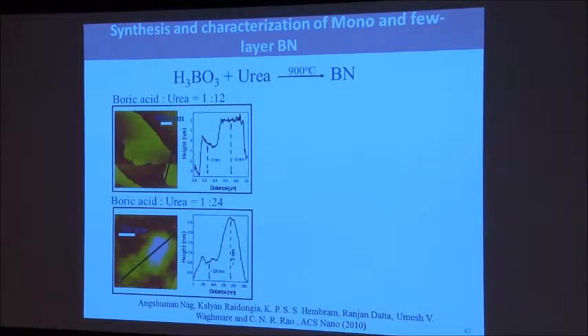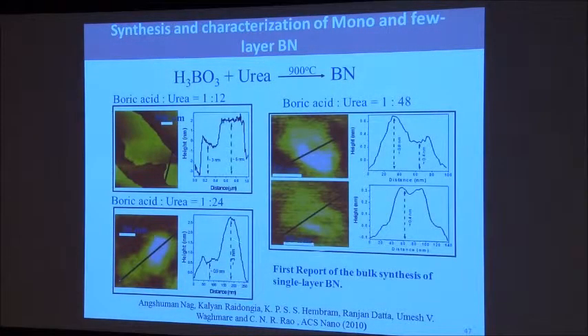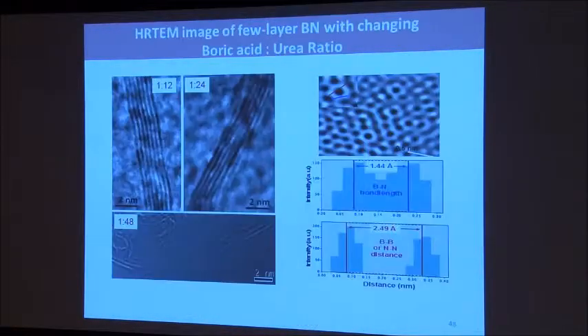Some years ago, 2-3 years ago, we made a very nice boron nitride by a simple high temperature reaction. A lot of people use this method. A single layer boron nitride, one sheet, you can see the thickness is only 0.4 nanometers. We could make boron nitride of various forms. You can see these pictures. These are one layer of boron nitride, just like graphene.